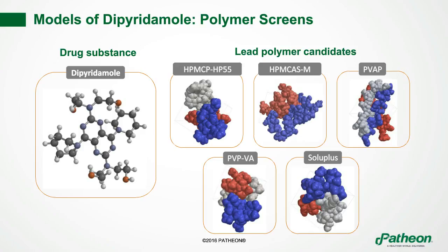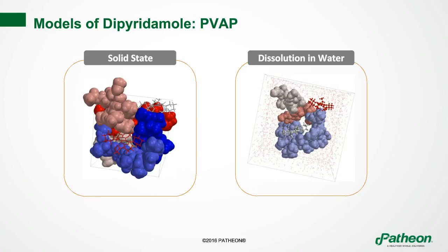And so what we have in this slide would be the solid state of the drug and polymer interaction. And this is very akin to what you would find in a drug development program, where you have the drug molecule shown in the stick figure and the polymer shown in the space-filling model, the balloon-type model. And what we see is the drug is binding in pockets. And these are largely, what we have found, places where the complementary descriptors interact with each other. And these binding energies can be anywhere from 10 kilojoules per mole to 100 kilojoules. Now, in these simulations, we're dealing with anywhere from 10 to 50 drug molecules in these small-scale molecular dynamics.